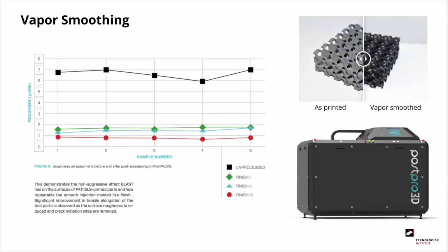Another option for surface treatment of SLS parts is what is called vapor smoothing, which is a technology that seals the surface in a machine like the one you see in the bottom right corner. In the picture above, we can see on the left what the part looked like immediately after printing, and on the right what it looks like after vapor smoothing. The process melts the surface together, and if we take a look at the graph on the left, we can see that the black line represents a part that is untreated and has been surface roughness measured. The lower lines show that depending on which program we run, we can get a lower surface roughness.